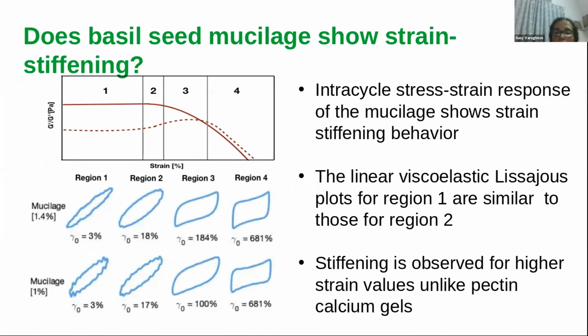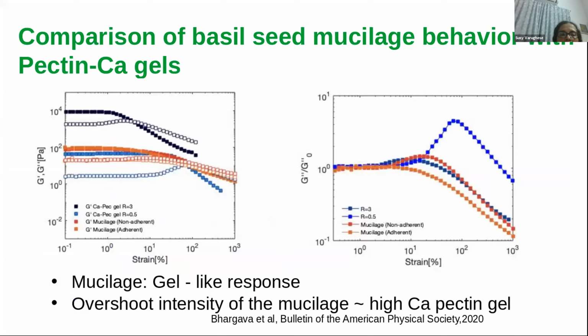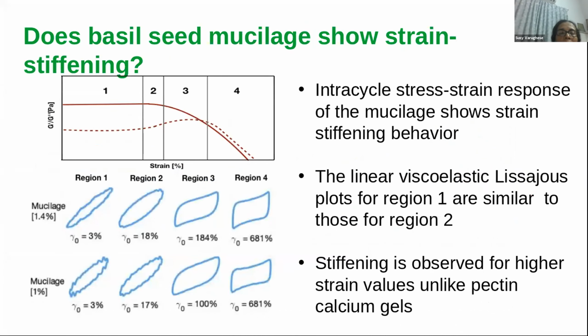So then we ask this question: does this seed mucilage, if you take it directly from the seed and do a similar experiment, show this strain stiffening? As you can see in this picture, this is again mucilage taken out and rheology done. We have compared the mucilage rheology with the rheology of pectins at different concentrations. One can see that they do show some amount of dissipation, where dissipation means there is a peak in this G double prime by G prime. The intensity is low, but it's there. But these experiments are still going on, to confirm how much strain stiffening or dissipation can happen in seed mucilage, for example.